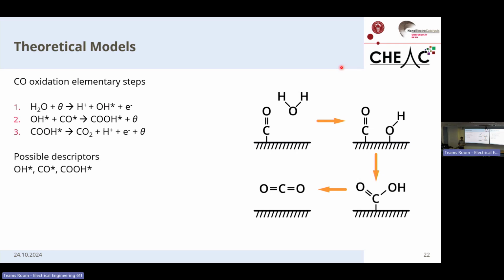For that, we went back to our theoreticians. So I asked Jack to come up with a theoretical model that can explain the CO oxidation reaction. Breaking down the CO oxidation reaction into elementary steps, we end up with these three major steps. In the first step, we have CO bound to the surface, and we need to bind an OH next to it. After that, the OH and CO combine into a COOH molecule, and then CO2 leaves the surface. So if you now look at the descriptors for this reaction pathway, we have three types of binding energies we can look at.